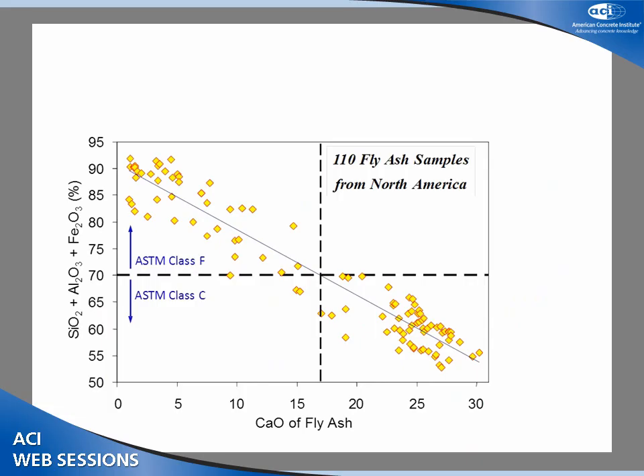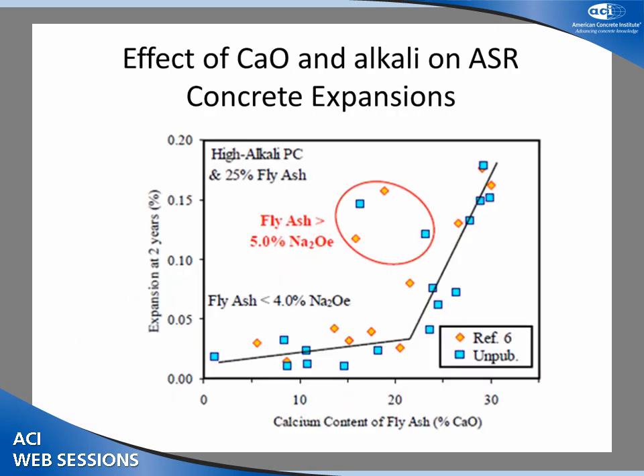Okay. So in terms of how that relates, as I said before, this is some of Mike Thomas's data that he's pulled together, comparing how you would classify things in ASTM on some of the oxides versus calcium oxide. And the 70% sum of the oxides, if you draw through the median, the best fit line is around 17%. But when you get down to the noise in the data, it's about 15%. So in terms of performance, I'm pretty comfortable with the 15% being similar. So an F ash on one side of the border is pretty much an F ash on the other side of the border. Okay. Now I mentioned the calcium content.